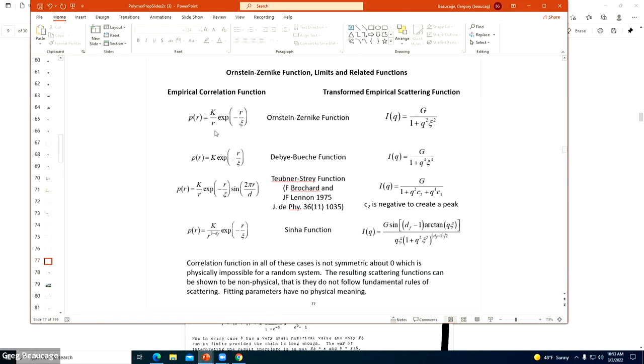In the power law region, it's known that this would be R to the 3 minus DF. The transform of Q to the minus DF is this thing. A power law transforms to a power law. Then he used this and called it a cutoff function. Here it was arbitrary, here it's arbitrary, so he introduces an arbitrary cutoff function. He was able to Fourier transform that whole thing and get this, which does what it says it's going to do.